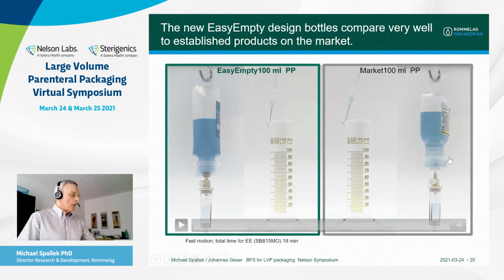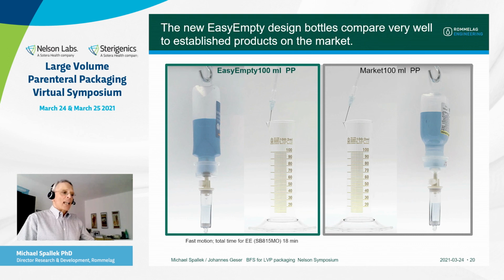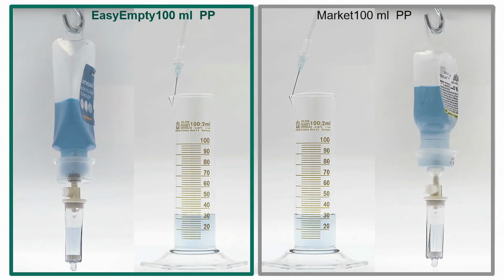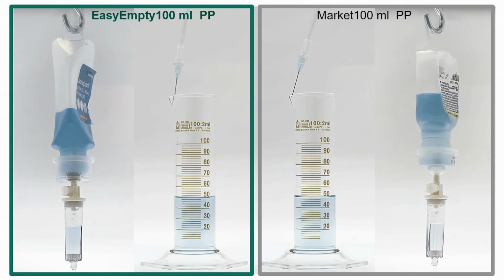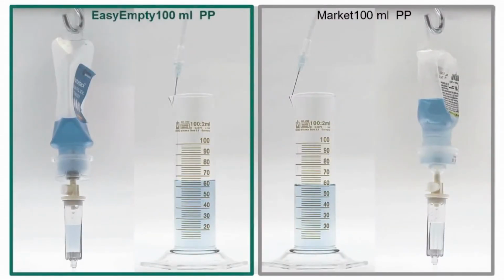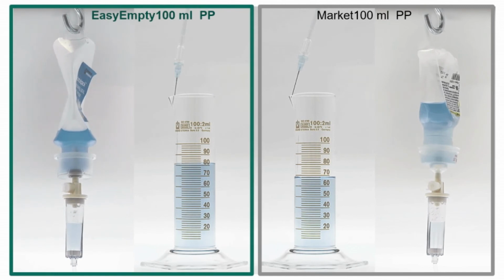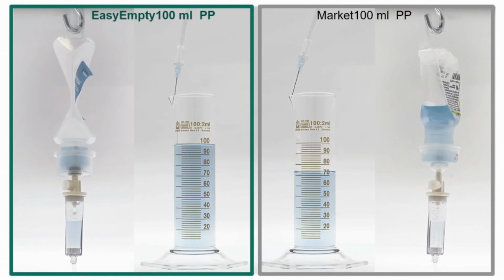You see the results here. On the left-hand side, this is our easy empty bottle, 100 ml, made from polypropylene. On the right-hand side, it's a bottle from the market, an existing bottle from the market. And now we can compare. Starting the video, we are emptying the container now into that cylinder. This is a fast motion, otherwise we would need 18 minutes more until the easy empty container is empty. You see at the beginning they are quite similar, but now at the end of administration, the easy empty container is very superior, empties completely after 18 minutes, whereas it takes much longer for the standard polypropylene bottle from the market. This was the proof that simulation and reality nicely fit together, not perfectly, but quite nicely.